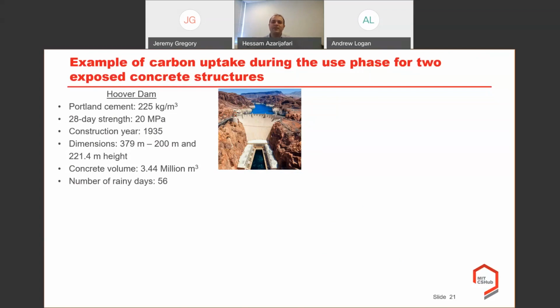Here are some interesting results that you might want to hear about: the Hoover Dam, one of the largest exposed concrete structures in the U.S., with a Portland cement content of 225 kilograms of Portland cement per cubic meter of concrete, and a 28-day strength of 20 megapascal. The construction year was 1935, and here you can see the geometry of the dam and the total amount of